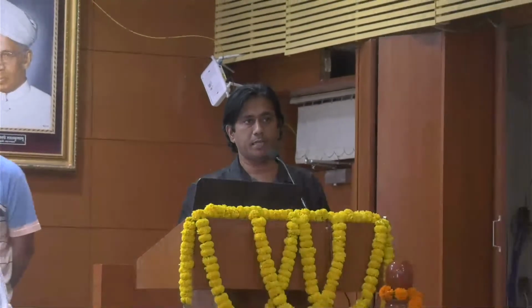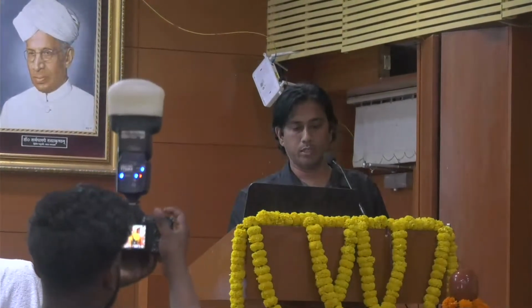So moving on, the holes which are created by the ion beam. The ion beams are generated by the ion source. This is the ion source we have used, a low energy broad beam ion source, 50 electron volt to 12 kilo electron volt, which is in collaboration with IOP Bhubaneswar.